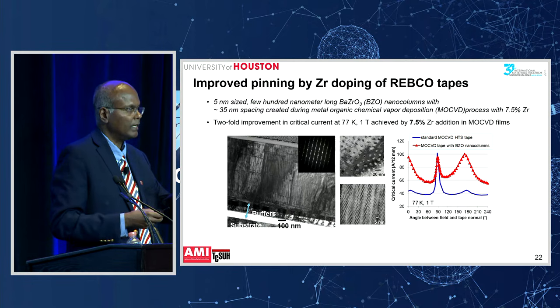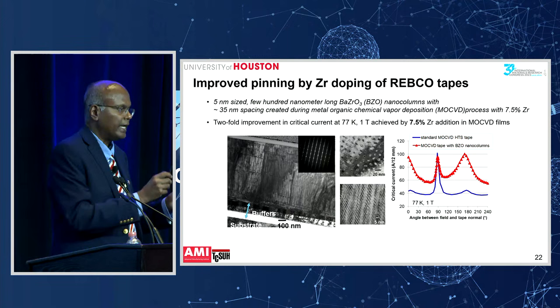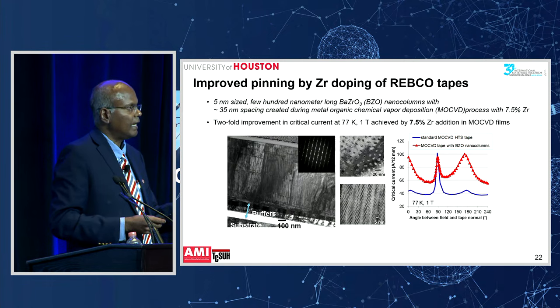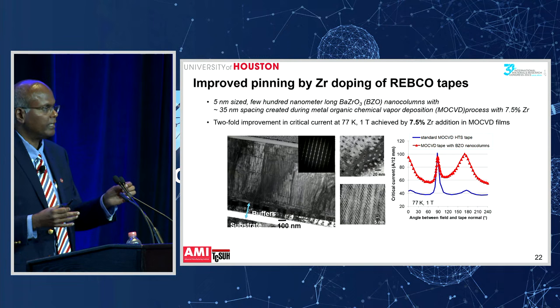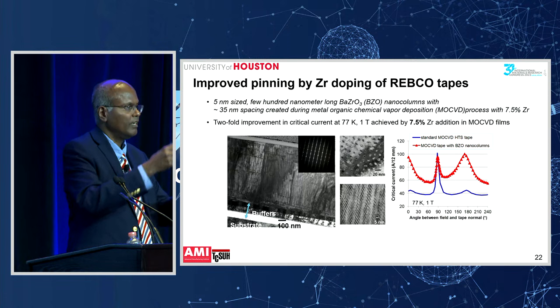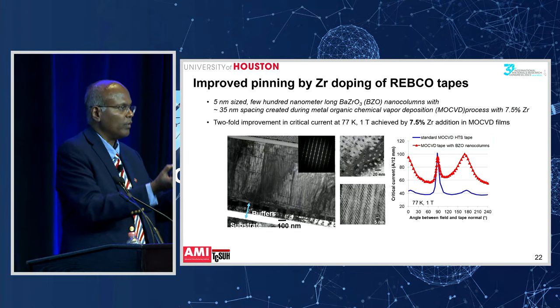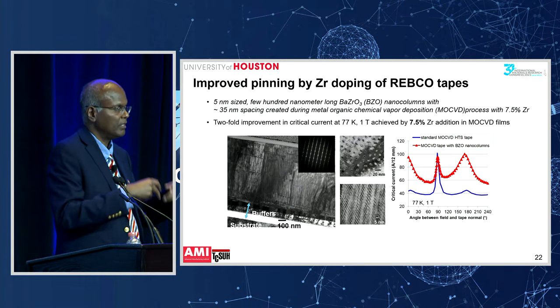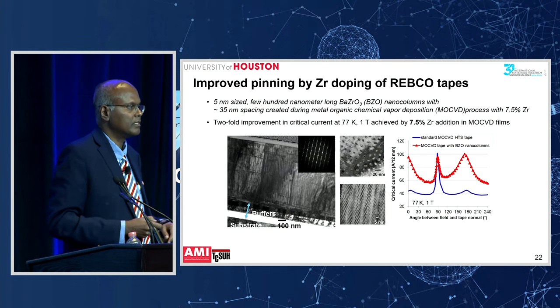So the beauty is that these nanorods are growing on top of themselves. The reason is this barium zirconate has a large lattice mismatch with the superconductor, about 8 to 9% lattice mismatch. So the barium zirconate does not want to grow on the superconducting film. It wants to self-assemble on top of itself, so the barium zirconate is growing by itself, and the superconducting film is epitaxially growing. So you can do epitaxial film growth and self-assembly growth simultaneously in the same film, in the same process. So that's what is done. And when you do that, you can see the difference in the performance.